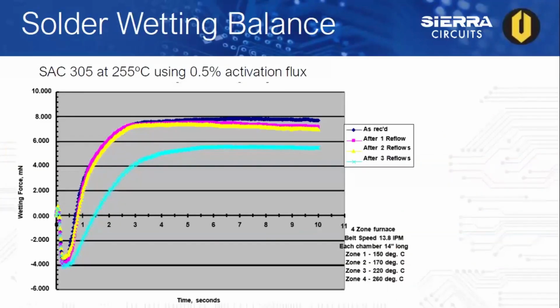Now, during wetting balance of the ENIG finish, 4 tests were completed, involving soldering SAC 305 at 255 degrees Celsius using 0.5% activation flux. The conditions of the samples analyzed were as received, and also samples after 1, 2, and 3 reflows.